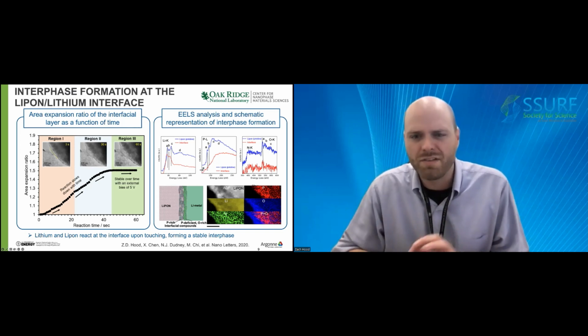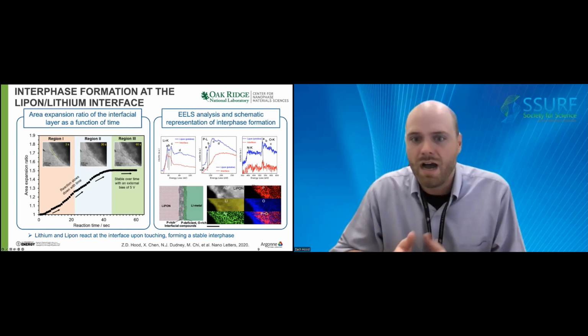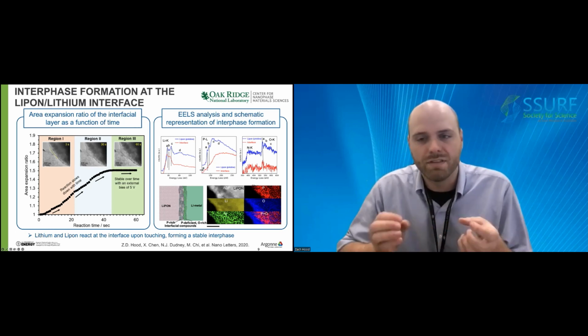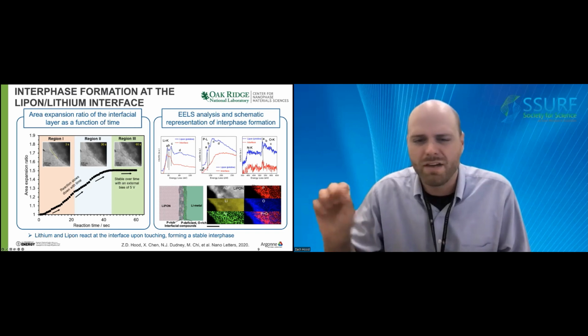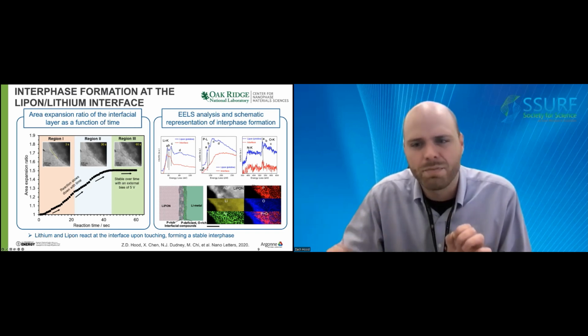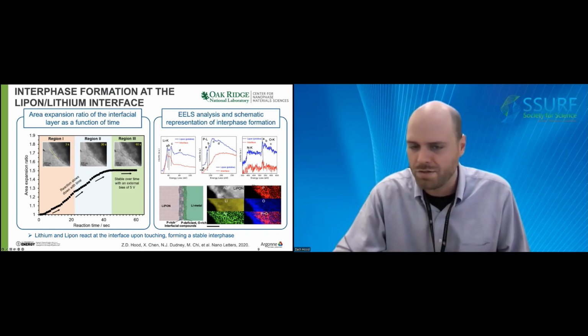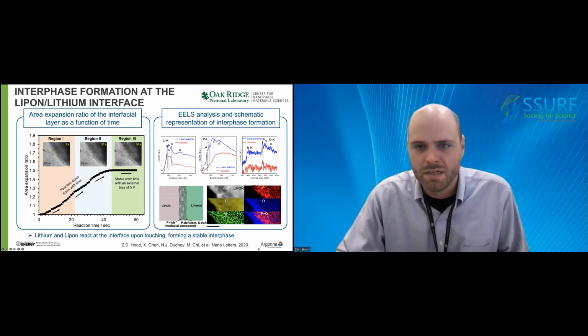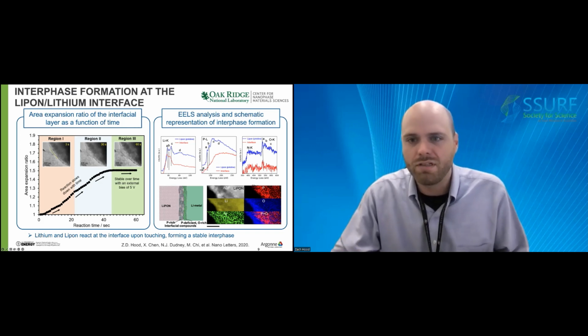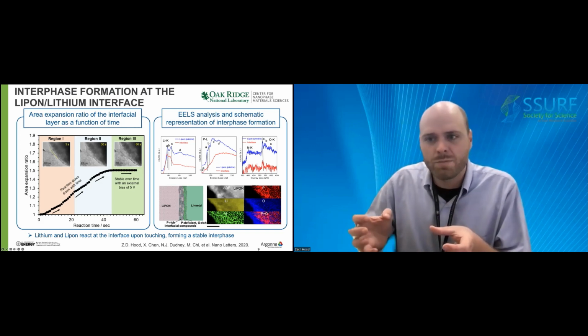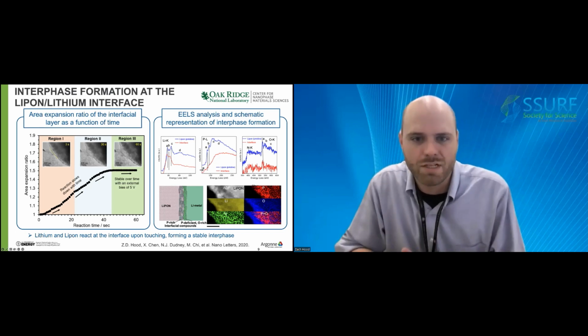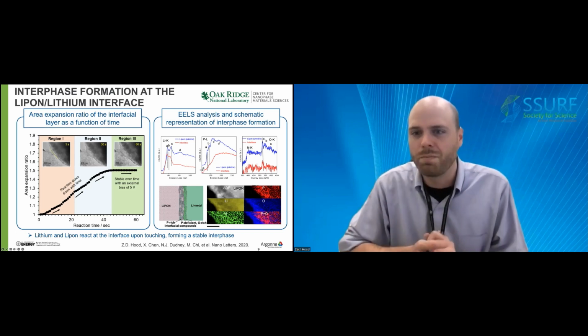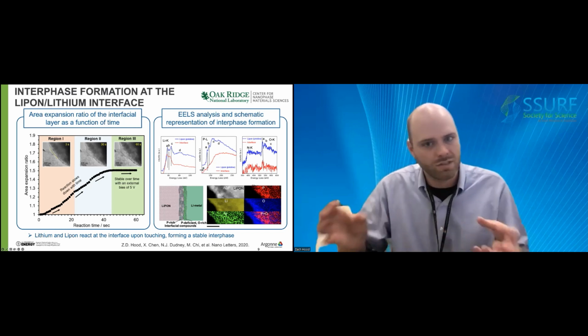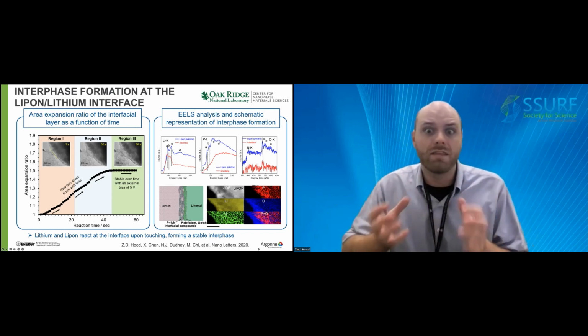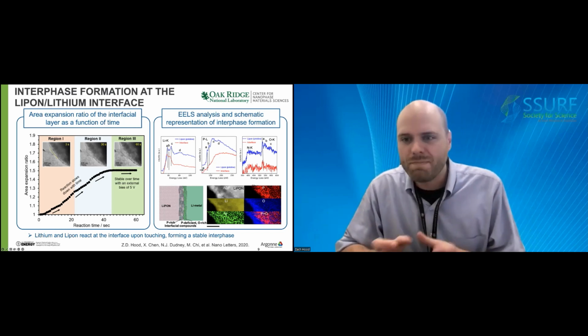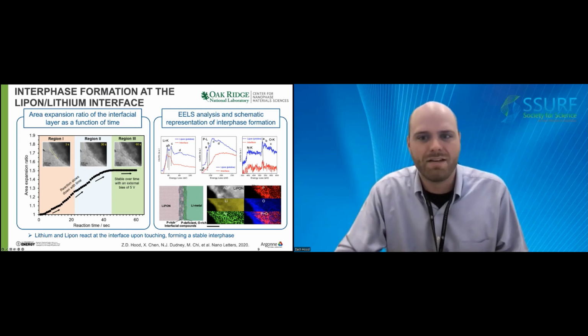It is also interestingly noted that the nearest neighbors of the lithium in LiPON are primarily oxygen and nitrogen, based on previously reported theoretical calculations and neutron scattering. So our microscopy results, including both these in situ imaging as well as our electron energy loss spectroscopy analysis, provided two important points regarding the stability of our solid-state electrolyte LiPON with the lithium metal anode, which is schematically shown at the bottom of this slide.